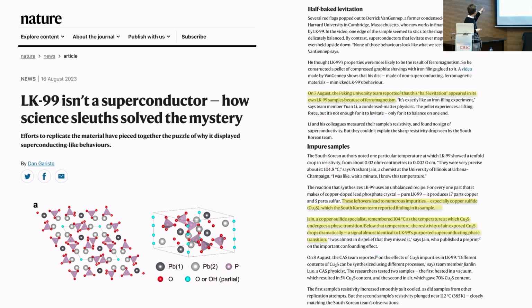This is Dan Garisto, a reporter who wrote for Nature, and he was saying, okay, this is already clarified. The magnetic signature is probably ferromagnetism. That's what people were saying. And then it seems that the copper sulfide impurities in this material have a transition precisely at that temperature that drops the resistivity a lot. So the pieces merge together, and apparently this material is an insulator as well. Therefore, it seems that the debate was over.